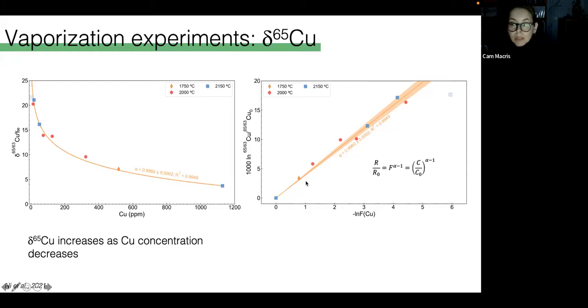Well, if we look at the equation for Rayleigh evaporation shown here, which describes the partitioning of isotopes between two reservoirs as one reservoir decreases in size. So here, R is the ratio of copper isotopes in the residual melt. This is what we measure in our experiments after heating. And this is over the initial ratio. And this is what we measure in our starting materials. F is the fraction of copper remaining in those experimental glasses. And then alpha here is the fractionation factor. And that's what we want to know. So we can see also from this side of the equation that the fraction of copper remaining is simply the concentration of copper in the experimental residue divided by the starting material.